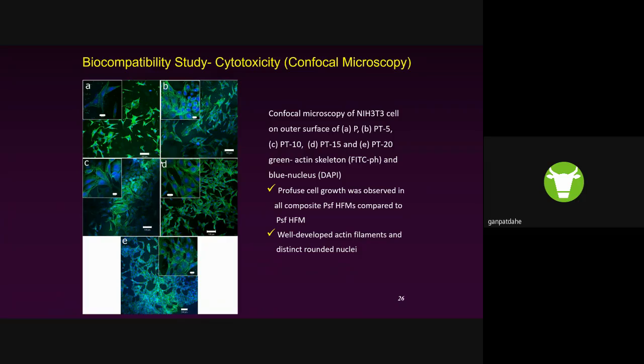They're growing, and this cell growth is very profuse. And as you can see, this cell growth density increases with increasing vitamin E TPGS content, which is a quite encouraging result.